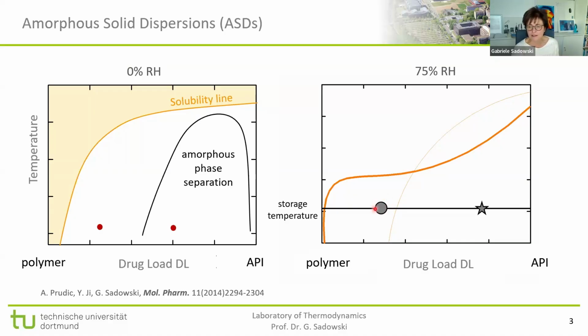But if we now have a tablet and we store it at humid conditions, it will absorb water. And as the API is very hydrophobic, the polymer usually is much more hydrophilic. The low drug load samples absorb much more water than the hydrophobic ones on the right-hand side. So that means for our tablet that this point, which was safe at dry conditions, now at humid conditions after water absorption becomes supersaturated, because now it's far right of the solubility line in a water-containing system, and it will crystallize during storage.